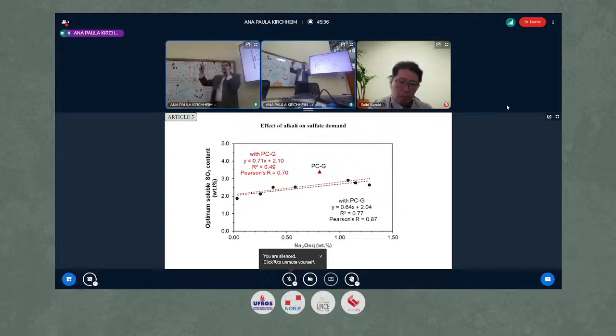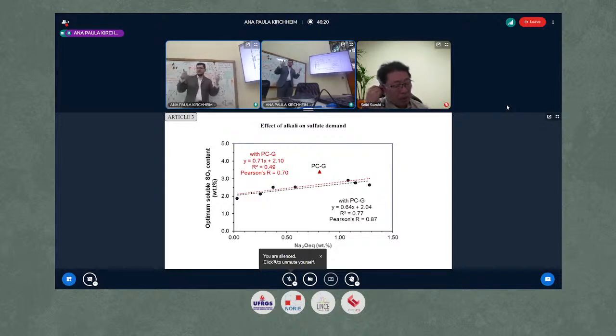The greater the alkali, the greater the optimum sulfate content. Because alkali increases clinker reactivity, meaning more CSH, absorbing more sulfate, and meaning more ettringite consuming more sulfate. So we accelerated sulfate consumption, so we increased optimum sulfate. PCG, again, was an exception. Why? Because PCG, as I will explain later, had a very high silicate peak. This means that it has a greater alite reaction. I don't know why it has a greater alite reaction, but it has. So a higher alite reaction means more CSH, more sulfate incorporated in CSH, so more